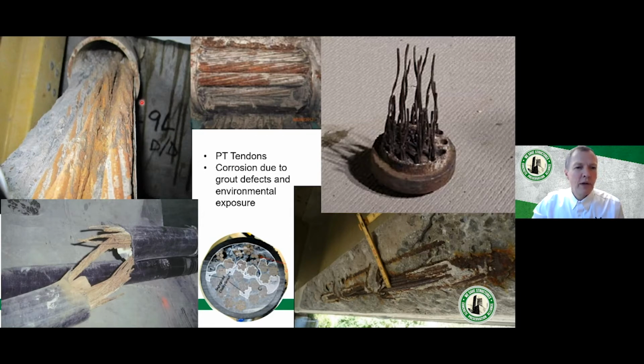The tendon here in the upper left-hand corner, as well as the one in the upper right-hand corner, are both examples of where you have voids in the grout. Obviously when there's no grout there, you don't have the protection that you expect on the tendons, and they're vulnerable to corrosion. That's one issue, and we'll talk about that later. The two pictures in the center are situations where you have segregation of the grout. In the bottom case, you can see segregation and the tendon is not fully full of grout. Sometimes water may float to the top and then you have a void left over later on. In other cases, the tendon may be fully full of grout, but because of segregation, you have good quality grout at the bottom and maybe not so good at the top, and you get corrosion.